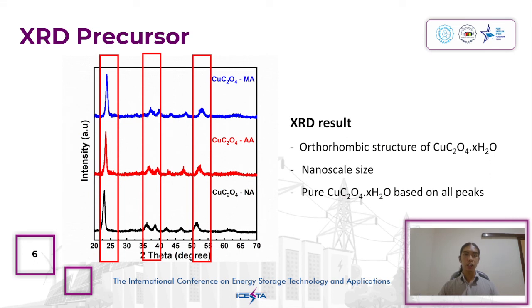Here is the XRD of the precursor. The XRD curve of each sample, malic acid, acetic acid, and nitric acid, demonstrates relatively wide peaks at each diffraction, indicating the average primary particle size at a nanoscale. The crystal structure analysis of the hydrate of each sample suggests a pattern corresponding to the orthorhombic space group.